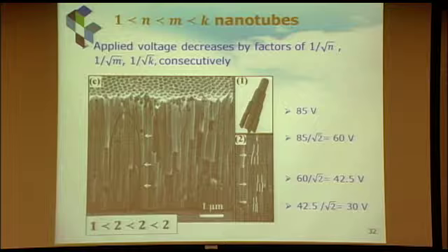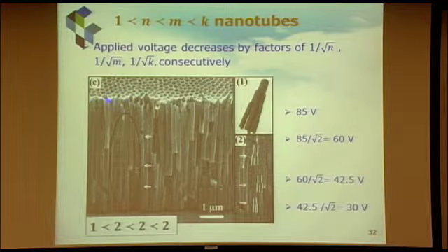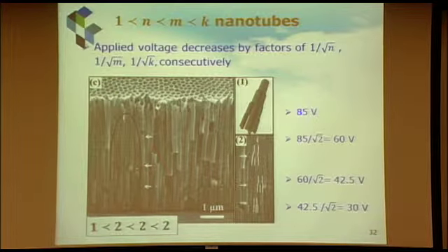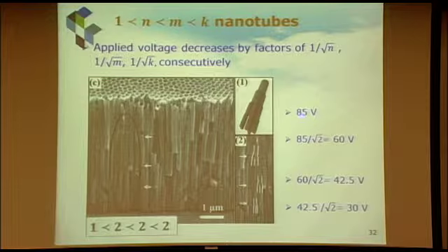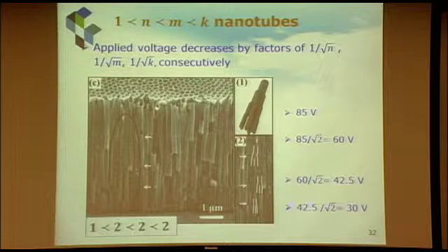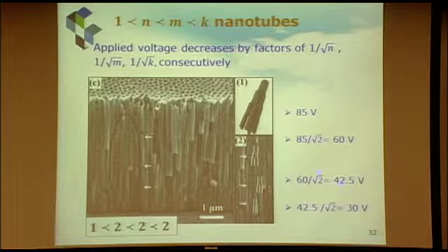And here is 4 steps. The one point to say is, remember we are working in a voltage range. We cannot change this randomly. We have to make sure the pores are still formed. So this is within a range, and we can only change our voltage within that range. So this goes 2, 2, 2, and then we can create 4 layers of pores.